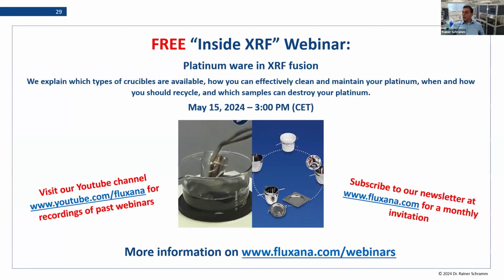Another question: how important is weighing? What tolerance do you recommend? Weighing is very important, but more important is the dilution ratio between flux and sample. This must be correct, okay? The absolute mass of liquid or the absolute mass of your bead in the end is not important. But you always have to keep the ratio, let me say 1:8, to get a reproducible fusion. And the tolerance I would accept is the same than your relative error you allow. So if you allow an error of 0.2% relatively, then this is of course the max you should allow in the weighing.